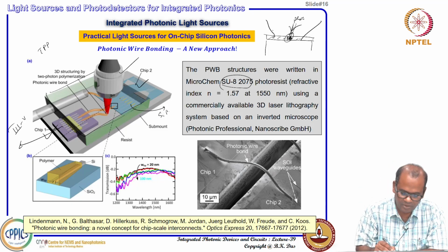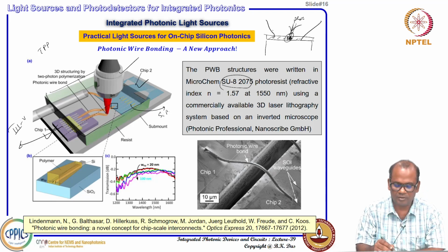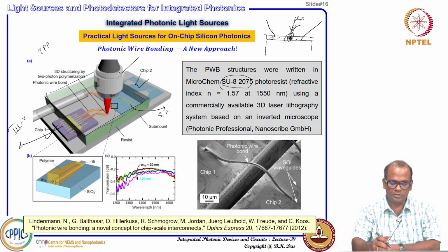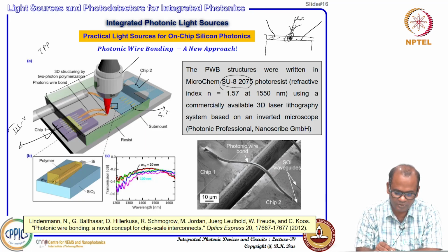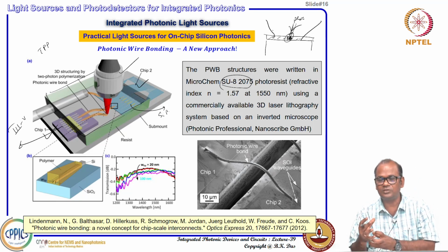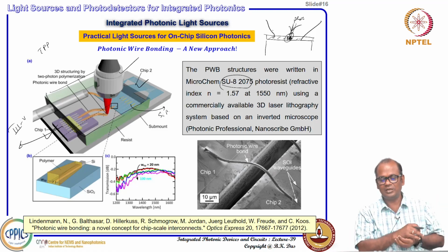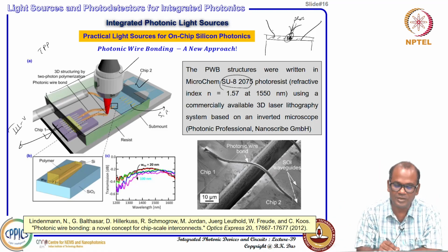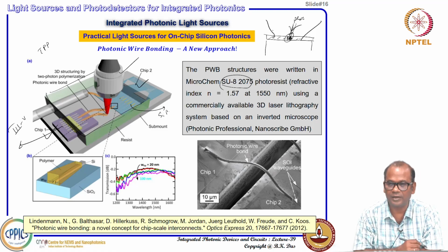Now, this laser beam comes here. You can use this laser spot size to define a certain type of polymerization, 2-photon polymerization. You see these pink color things. As you move your focused beam from this region to this region, for example this contact pad region, that particular region will be polymerized, and if you put in a developer, the rest of the region will be removed and only that hardened portion will stay back.